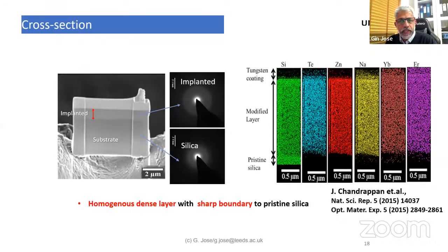You create a sample of that, and then you can put it in a TEM and do an elemental analysis of that doped layer. Here we can see we started with a silica glass, so that's why the silicon is present from top to bottom. You can see the silicon from there to here. That's where the interface of the change is. And then you've got the tellurium, zinc, sodium, which all stop there. There's some signal noise in there, but it basically stops there. So it's all coming from zinc, sodium, ytterbium, and erbium. All these elements are coming from the target glass that we ablated and then used to modify this silica glass.